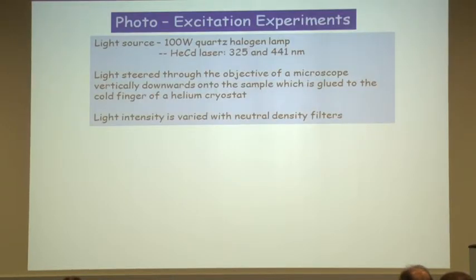All right, now I would like to talk to you about the second perturbation. It's a very exciting experiment. This is when you shine light on this, something very remarkable happens. So what we have used is two sources of light. One is about a 100 watt quartz halogen lamp, and the second one is a helium cadmium laser. It gives two wavelengths, 325 and 441 nanometers. The intensity of 441 is 10 times more than 325, a much brighter blue line than the UV line.